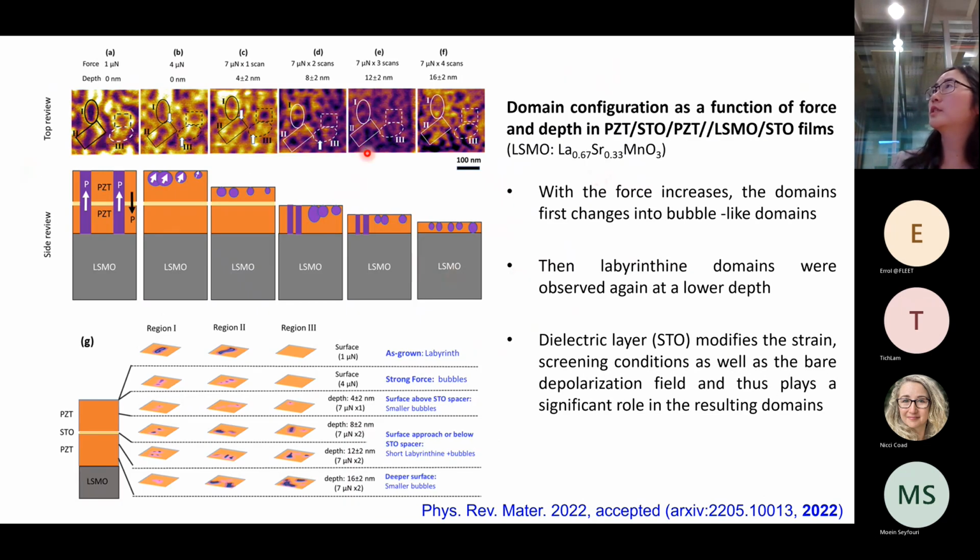So this image shows how the domain changes with removing the material layer by layer. We can see that this labyrinth domain starts shrinking into these nanoscale domains. And it still shows really high amplitude, as I mentioned, which we believe indicates these tilted topological configurations.